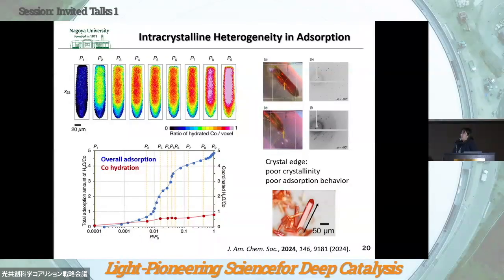And we also found some part with a poor adsorption behavior at the edge side of the crystal. And this trend is found for all crystals in MOF-74. And by the analysis of X-ray diffraction at this top side, this shows us the poor crystallinity. And so that means some shape and crystal engineering is quite important to increase the overall performance of adsorption in the MOF crystals.